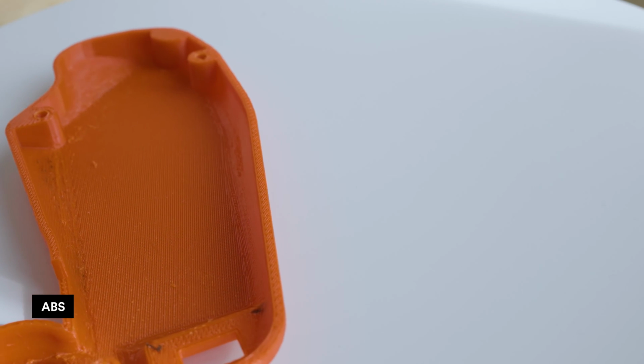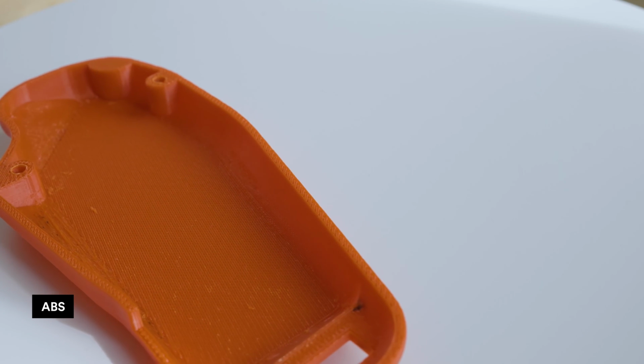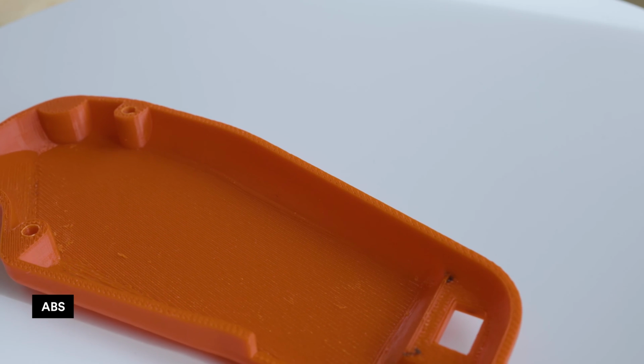Printing process. ABS is definitely harder to print than PLA. This is mainly due to the fact that ABS is a lot more sensitive to temperature changes during the printing process. For instance, ABS requires a higher print bed and nozzle temperature, where ABS needs a bed temperature of about 80 to 110 degrees Celsius, PLA needs a bed temperature of about 60 degrees Celsius.